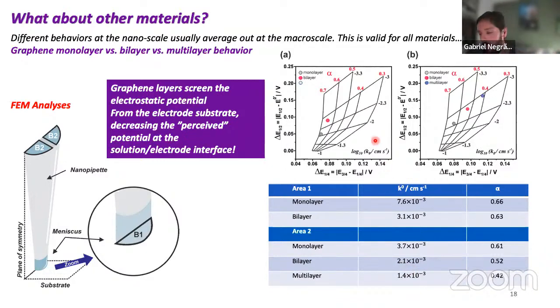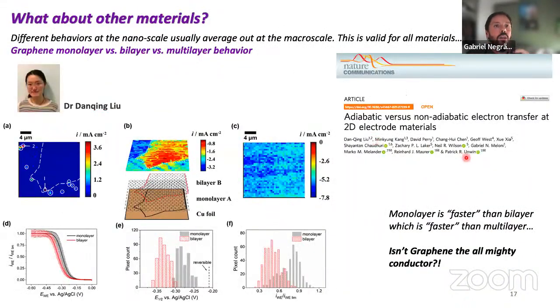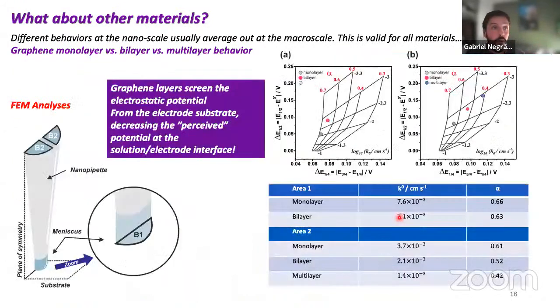And that's why even more brilliant people in this paper come in, a group that makes simulations, from Warwick as well. They did molecular dynamics and DFT simulations to calculate the potential across that graphene sheet. And you can see that there's a drop. The other layers of graphene are screening the potential. So I'm applying a potential to the copper, which is the electric contact, and the potential that my solution sees is screened by those graphene layers. And that explains quite well these kinetics. So even though this is an almighty conductor, very fast and very thin, it's still able to screen potential quite a lot, to a point that I see different kinetics for different layers.